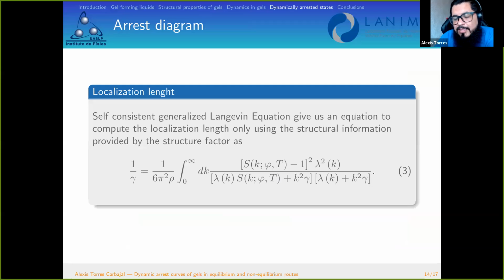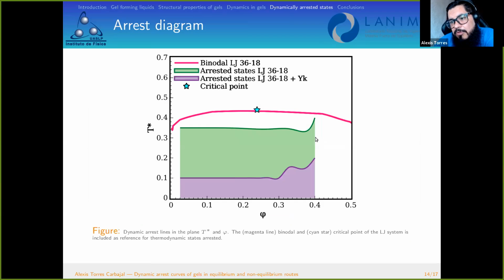So to characterize these arrested states, we used the so-called localization length provided by the self-consistent generalized Langevin equation to determine if the final state is an ergodic or a non-ergodic one. We use equation 3, which only requires the knowledge of the structure factor at the final time. And with this information and all the thermodynamics explored, we can determine the arrest phase diagram.